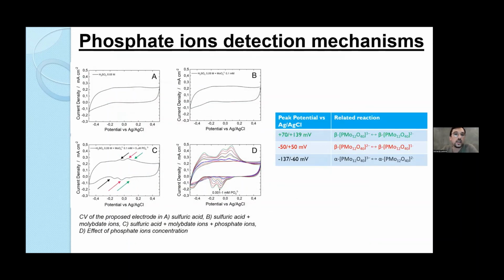So here we show the detection mechanism. In image A, we can see the cyclic voltammetry using just sulfuric acid, and it's possible to see there is no peak related to oxidation or reduction of the electrode. The same was obtained adding molybdate ions, so there are no reactions occurring using sulfuric acid and molybdate ions. But when phosphate ions are added to sulfuric acid and molybdate ions, three well-defined peaks appear, related to the oxidation and reduction of the Keggin ions of phosphate.